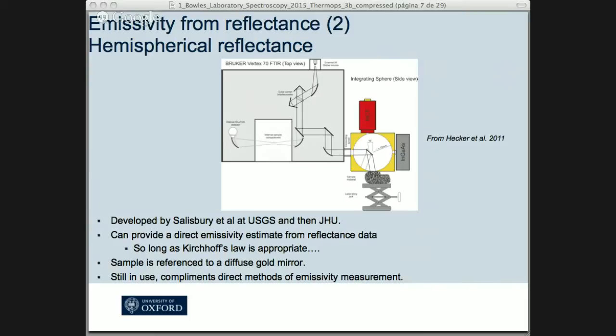Now, this provides a pretty good direct emissivity estimate from reflectance data, so long as you can assume that emissivity is equal to 1 minus reflection, which is not always true. It's still in use. A lot of people do this, and it complements other direct methods of emissivity quite nicely.